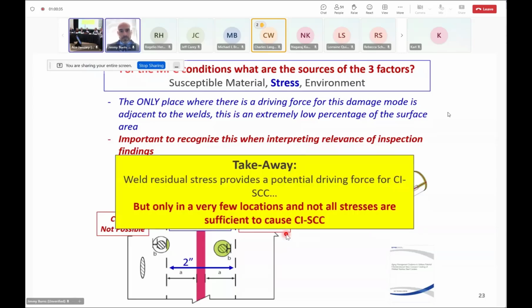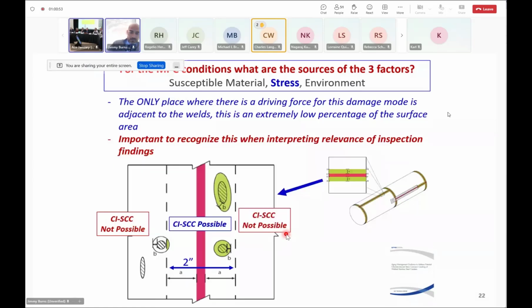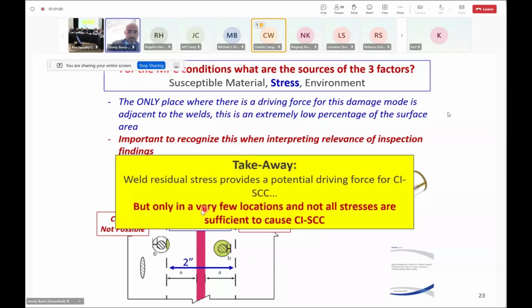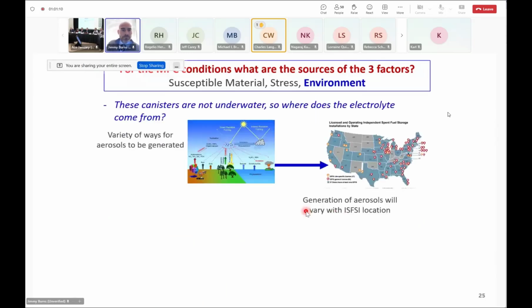So the takeaway from this little discussion is weld residual stress can provide a potential driving force for CISCC, but that's only in a very few locations. And remember what I said before, you could have stress here, you could have an environment, and you could have a susceptible material, but just because there is a stress doesn't mean that stress is sufficient to cause CISCC, okay? And then the final component that you need is an environment.